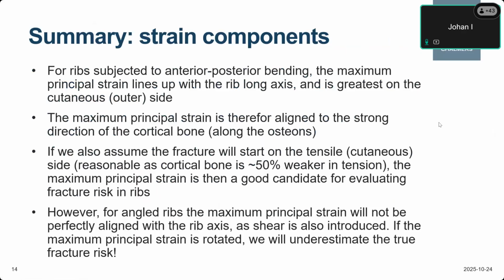But for angled ribs, and the more angled you have them, the more shear you introduce into ribs, then the maximum principal strain will not be perfectly aligned with the rib axis. So if the maximum principal strain is rotated, we will underestimate the true fracture risk.